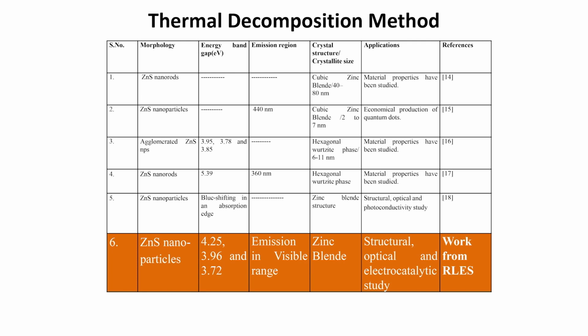In the case of ZnS nanorods, it is 5.39 electron volt, whereas in the ZnS nanoparticles there is blue shifting in the absorption edge, and the ZnS nanoparticles which we have developed in our lab have band gaps of the order of 4.25, 3.96 and 3.72 electron volt. The emission lies in the visible range, and the crystal structure which we have obtained is zinc blende. The potential applications which we have discussed are structural, optical and electrocatalytic study, and this is the work from our lab.